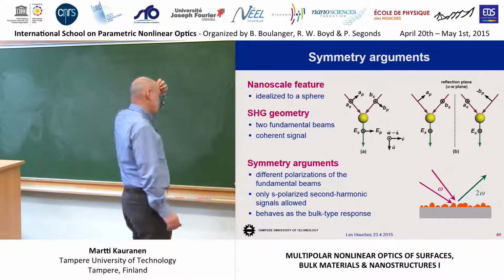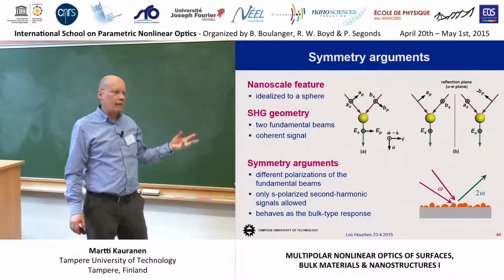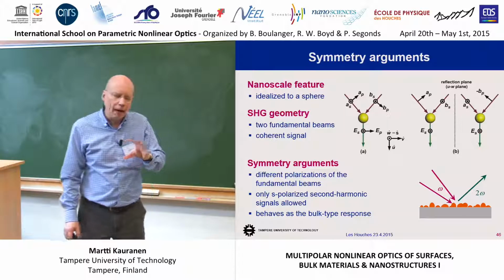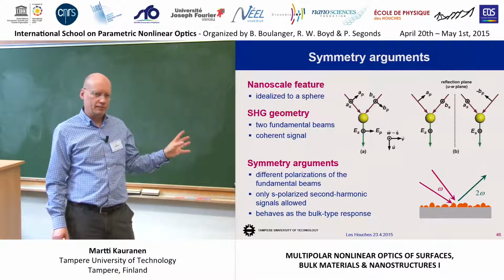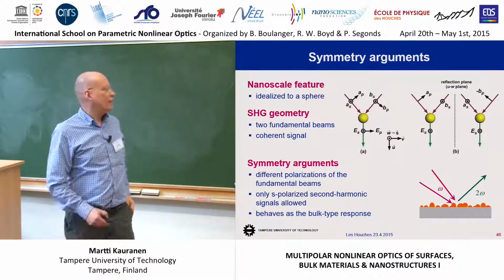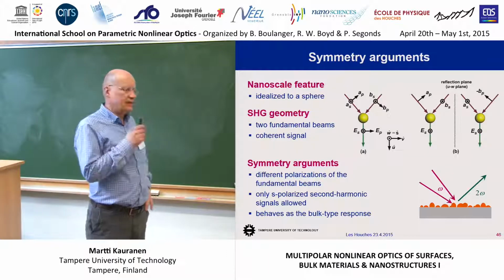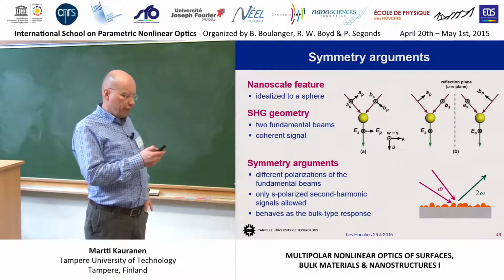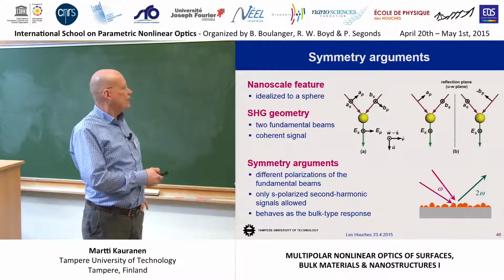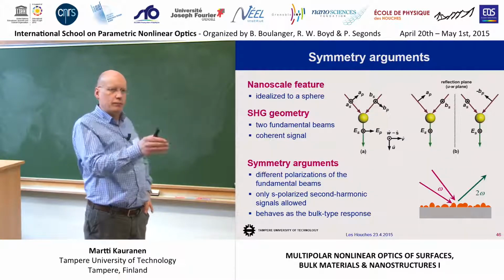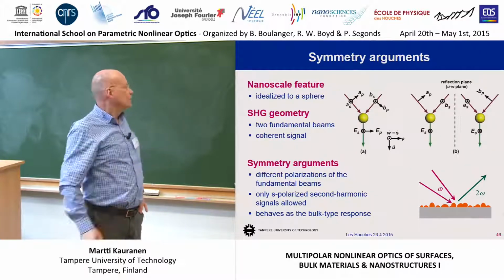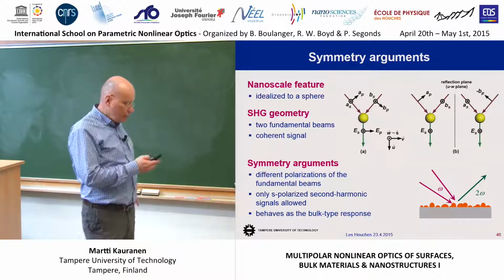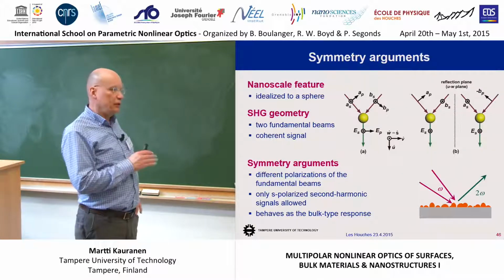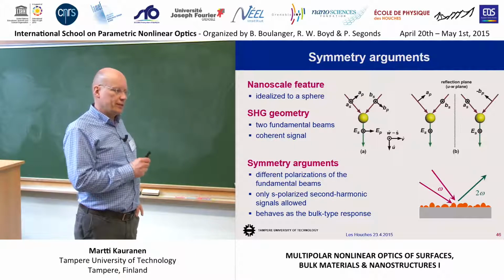We are trying to measure this fundamental bulk parameter due to magnetic and quadrupole effects. But then we get qualitatively exactly the same response from the fact that we have some nanostructure in our sample. So this means that we have to be really concerned about these things.